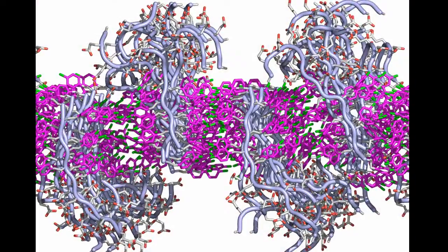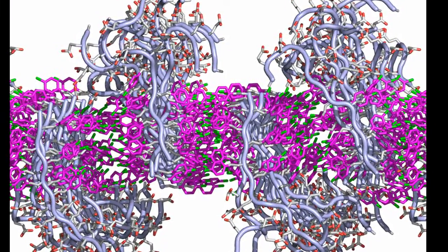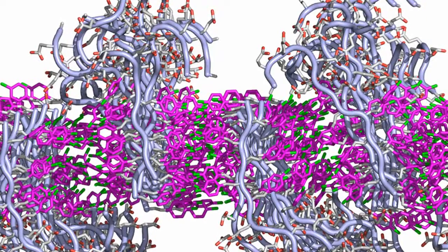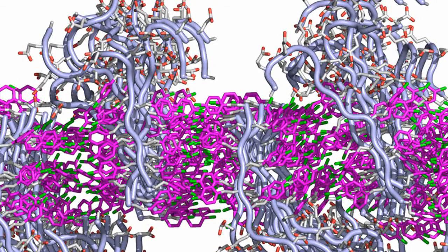The team then tested the nanomembranes to see if they could repair themselves, a useful feature for membranes that could get scratched during use. After cutting slits in a membrane, they added more of the lipid-like peptoids. Viewed under a microscope over the course of a few hours, the scratches filled up with more peptoid and the nanomembrane became complete again.